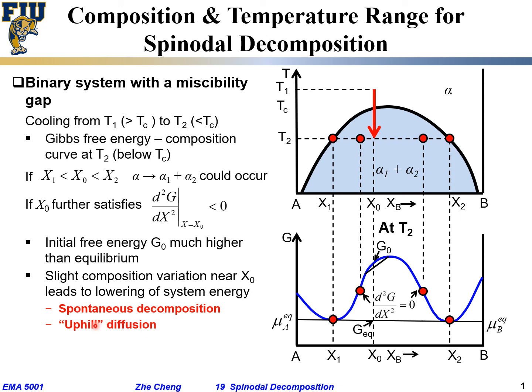The diffusion involved in this process is so-called uphill diffusion — not downhill diffusion. The solute atoms actually want to go to the region that is even richer in solute. The system always reaches equilibrium: starting from the single-phase point, it separates and eventually reaches the equilibrium state. It cannot stop at a metastable state.